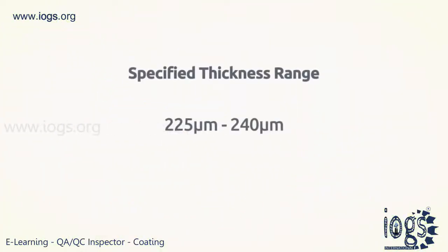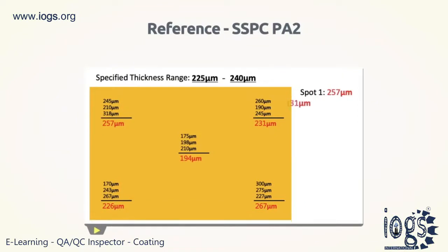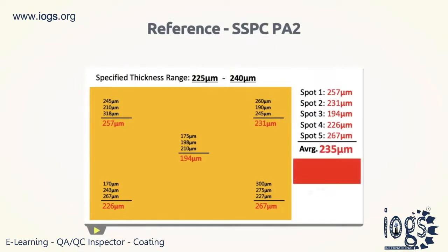For instance, a coating specification may demand the inspector to confirm the conformance of a coating thickness between 225 and 240 micrometers. In such instance, the 5-spot measurements of a 10 square meter area must have an average that is not less than the specified minimum thickness. Likewise, every spot measurement in all the 10 square meter area must not be less than 80% of the specified minimum thickness. A gauge reading of a spot that underruns by a significant amount would not be accepted.